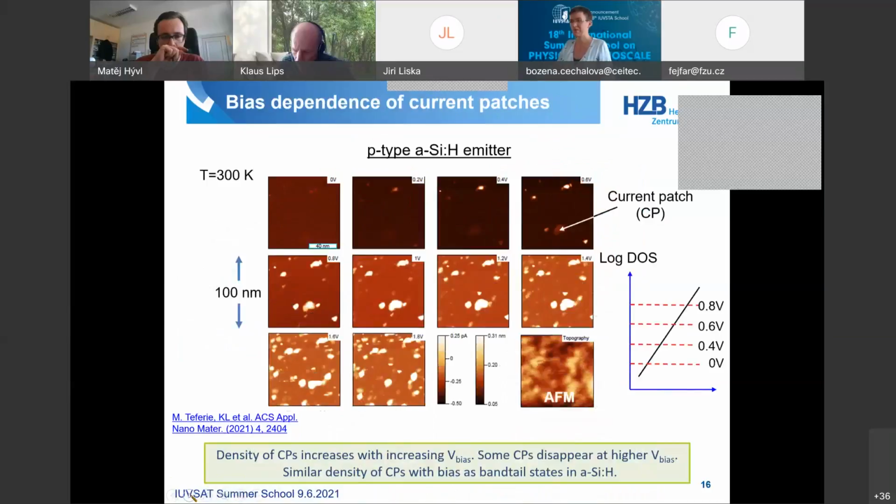Now, what you can do is you can now check on this behavior as a function of the applied voltage. So if you go towards that open circuit voltage, you should see changes. If you go beyond, you should only see a positive current. And that's what is happening. We start at 0 bias. So this here is 0 bias. That's short circuit. And then you increase the voltage, and you can see from a very homogeneous background, now suddenly spots are appearing. And that means with increasing voltage, we get more and more of these hotspots in that measurement.